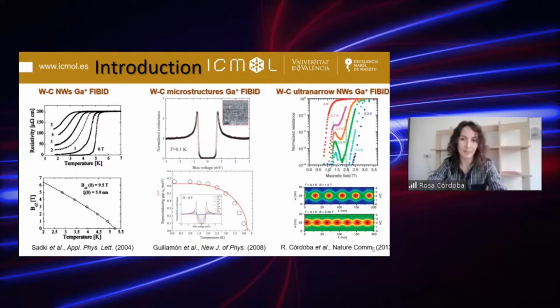And we have the possibility to make very narrow nanowires with the gallium beam, with just 50 nanometers in lateral size, and we observe a very interesting phenomenon: the persistence of superconductivity at a relatively high magnetic field, around 2 Tesla, due to the strong confinement of a single vortex at the center of this very narrow nanowire.